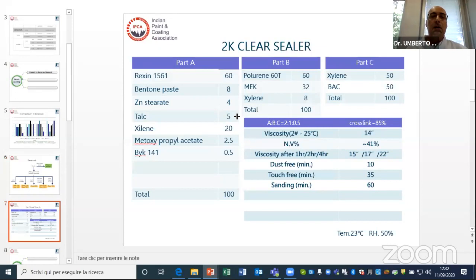Here we can see a formulation for clear sealer, very easy to realize and very, very often used by our customers. It is based on Rexin 1561, and it is catalyzed with our Polurene 60T. We can see that we have a very low viscosity when it is diluted with solvent. We have very fast drying and also very fast sanding properties of the same.